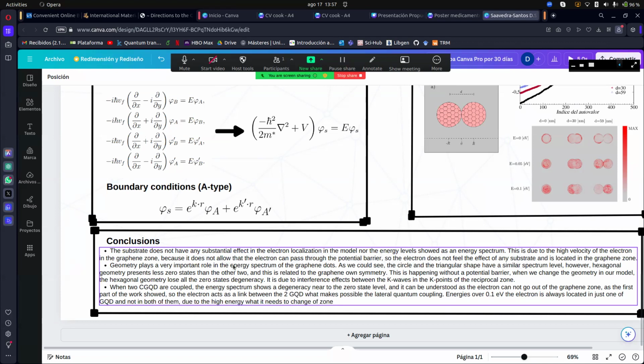We can say that the geometry plays a very important role in the energy spectrum of the graphene dots. As we could see, the circular and the triangular shapes have a similar spectrum. However, hexagonal geometry presents fewer zero states than the other two, and this is related to the graphene symmetry. This is happening without a potential barrier. When we change the geometry in our model, the hexagonal geometry loses all the zero states degeneracy. It is due to interference effects between the waves at the K points of the reciprocal zone.